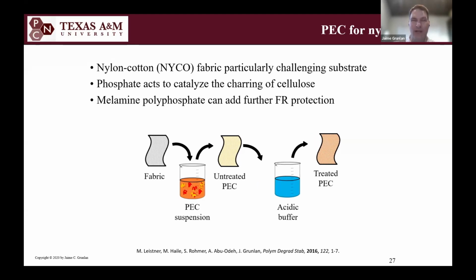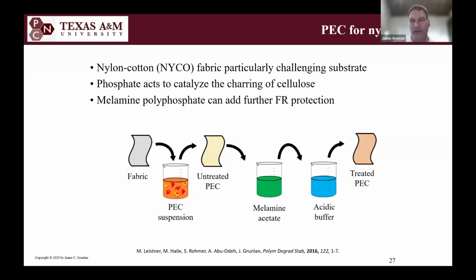And so we had to add an ingredient, and now it looks like I created a 3-step process. That melamine acetate, by the way, is a water-based solution that could be added to the PEC suspension, or it could be added to the acidic citrate buffer. But in any event, I took that original PEC suspension and then we added this melamine acetate. And what happens is you create melamine polyphosphate in situ, a water-insoluble molecule, and that actually can flame retard the nylon part of the nylon-cotton blend.